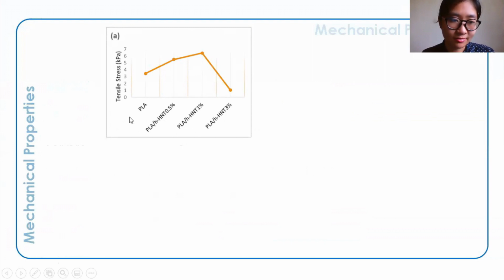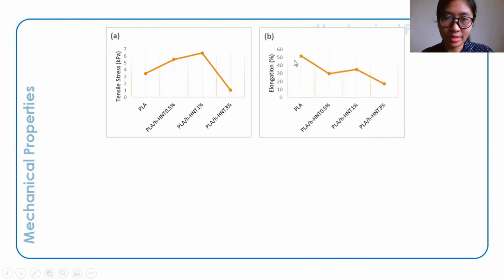In this first line graph, the sample with the highest tensile strength is at 1% HHNT, while the lowest is at 3% HHNT content. This is the force responsible for the stretching of the material. How long the material is stretched is also plotted here. Results show that pure PLA has the highest elongation and then it decreases with increasing HHNT content. What this means is that we go from an elastic material to a stiffer or less elastic material.